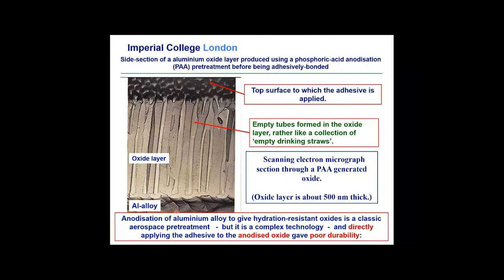This shows aluminium alloy. It's a section, so you're looking at a section through of aluminium alloy. The standard treatment for aerospace for aluminium alloys is to anodize. You put it into acid and pass a current through the aluminium alloy, through the solution, and this generates an oxide layer. This oxide layer is about 500 nanometers thick. This is the top surface to which you would apply the adhesive, for example. Here's the aluminium alloy underneath it.